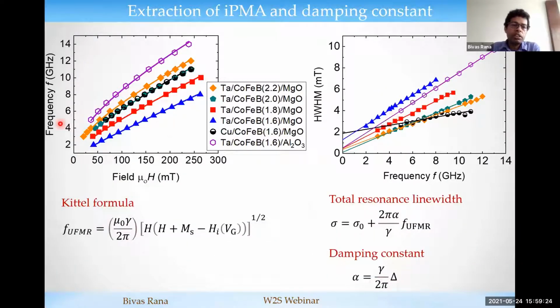Then we plotted the frequency as a function of the magnetic field and fitted with the Kittel formula to find out the perpendicular anisotropy and its variation as a function of gate voltage. And to find out the damping constant, we plotted the extracted value of half width at half maxima, the resonance linewidth, as a function of frequency. Then, using this formula, we just fitted with a linear function, and from the slope of this fitting we extracted the damping constant.